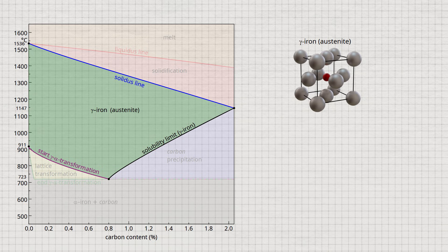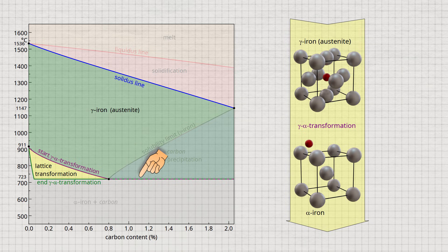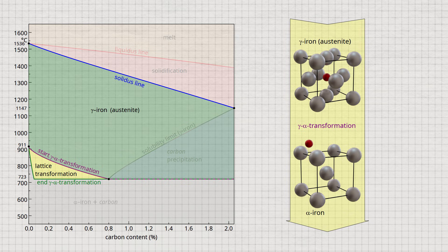However, the face-centered cubic lattice of gamma-iron begins to change to the body-centered cubic structure at a certain temperature. It should be noted that this gamma-alpha transformation also occurs at carbon concentrations above 0.8%, although it is not visually apparent as a region in the phase diagram because in these cases the transformation occurs at constant temperature. Unlike the face-centered lattice of gamma-iron, the unit cells of the body-centered cubic alpha-lattice are already occupied by an iron atom in the center.